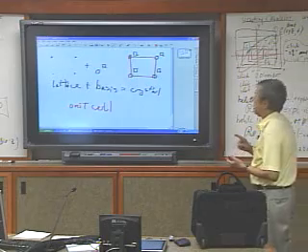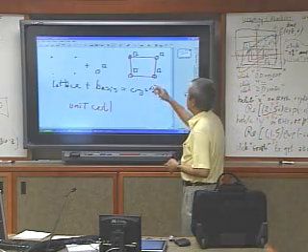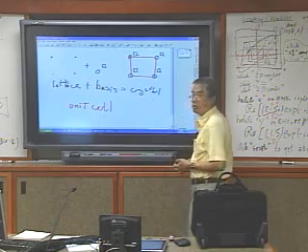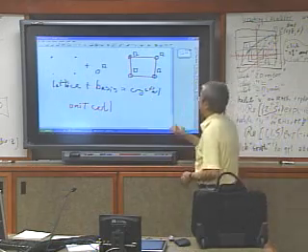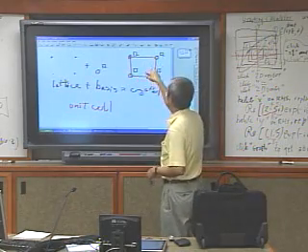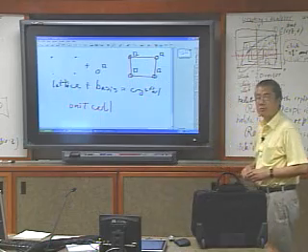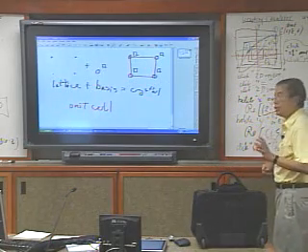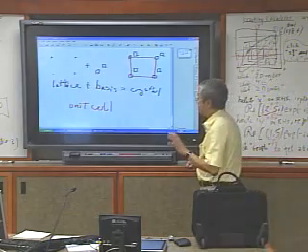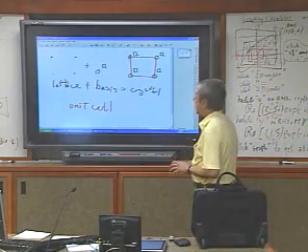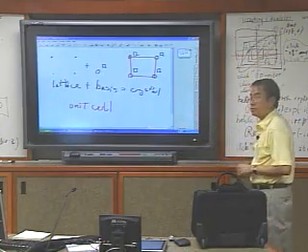The other thing is that if you want to know what the properties are, that is, if you want the symmetry of the properties, I should say, that is determined by the symmetry of the crystal. And the unit cell by itself, if I just tell you, well, you have atoms this far apart and so forth, you would have to go back and say, well, what is the point group or space group in order to deduce that information? So you need that information. So admittedly, it's harder to describe by using point group and space groups. Nevertheless, it is a lot more useful than the unit cell representation.